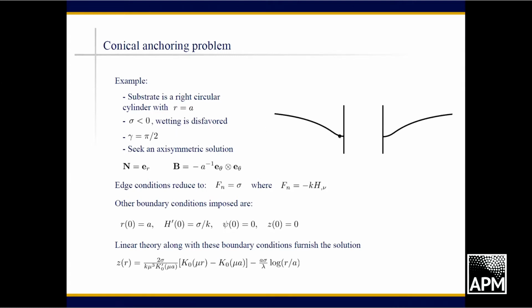That is, this is justified by the idea that the hydrophobic tail groups in the bilayer would then be shielded from the aqueous phase by the hydrophobic cylinder to which it's attached. The effect, in the boundary conditions, is to induce a transverse shear force on the bilayer, which is exactly this wetting energy.